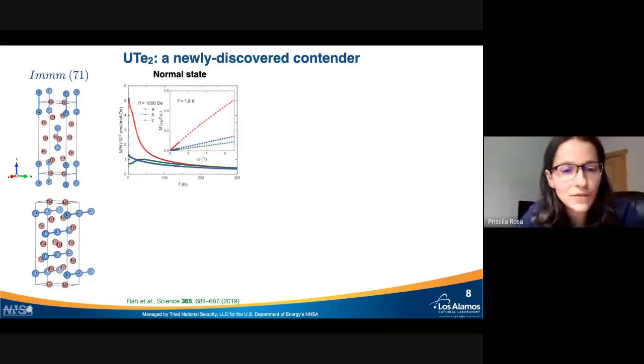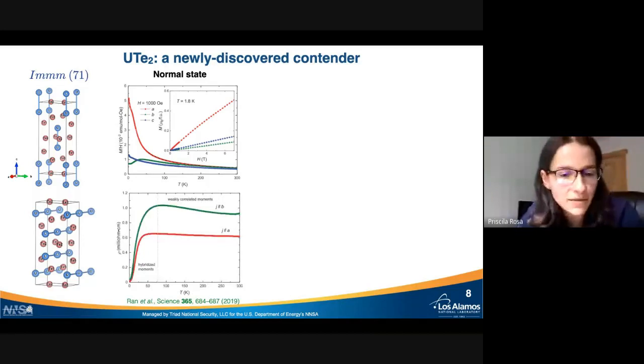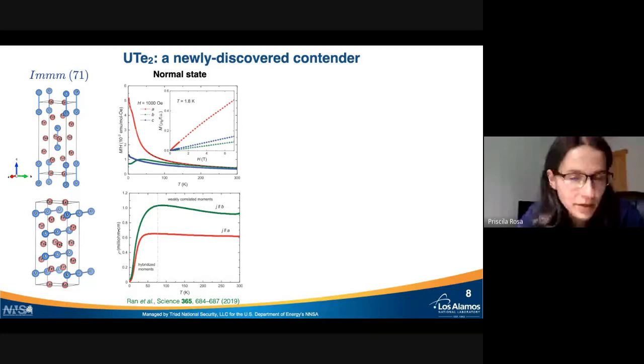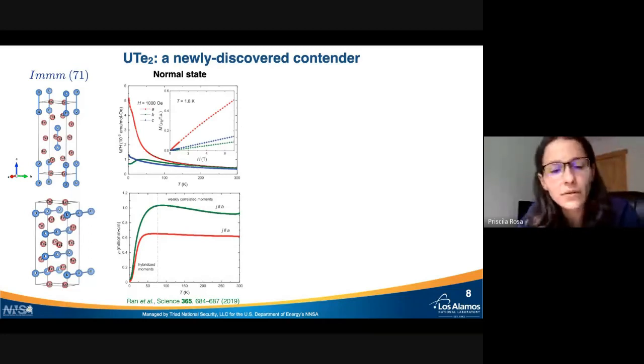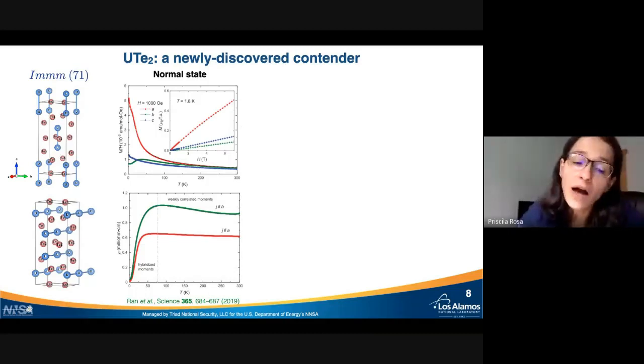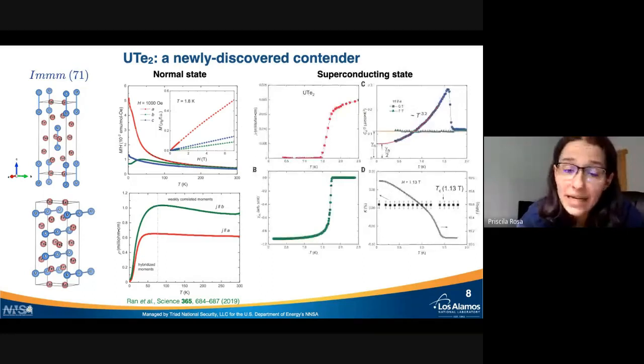This is the magnetization versus temperature. It is anisotropic, as one would expect from an orthorhombic material. It doesn't order magnetically. The resistivity versus temperature increases on cooling at first, when we perhaps have incoherent Kondo scattering, but at low temperatures, the moments start to hybridize and the resistance goes to lower values until at 1.6 Kelvin, it goes to 0.